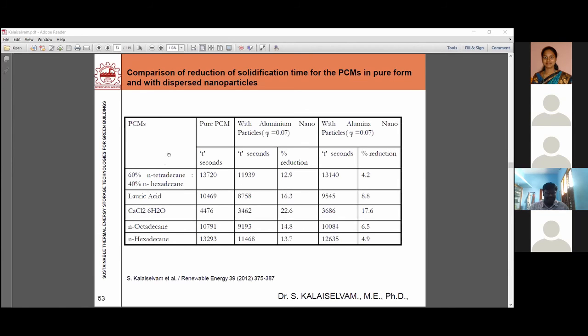So here we are using the pure PCM, that is 60% n-tetradecane and 40% n-hexadecane. It forms a pure PCM. By adding this aluminum nanomaterial, the solidification time is reduced by 12%. If we use the alumina nanomaterial, the solidification is reduced by 4.2%. In the case of lauric acid, the solidification is reduced by 16.3%. And if you use the alumina nanomaterial, it is by 8.8%. So these are all PCMs, and this is the reduction in the solidification time. By adding this nanomaterial, our PCMs solidify at a much faster rate.